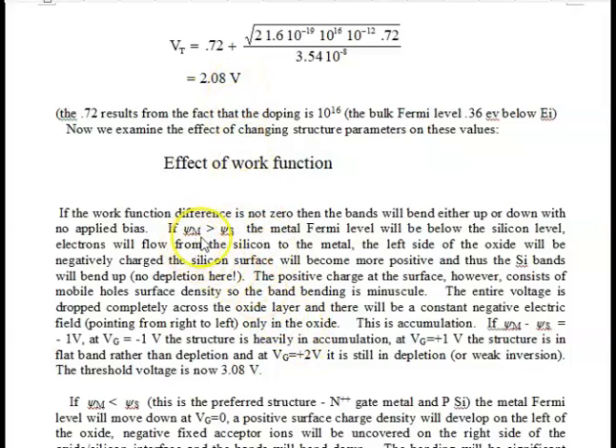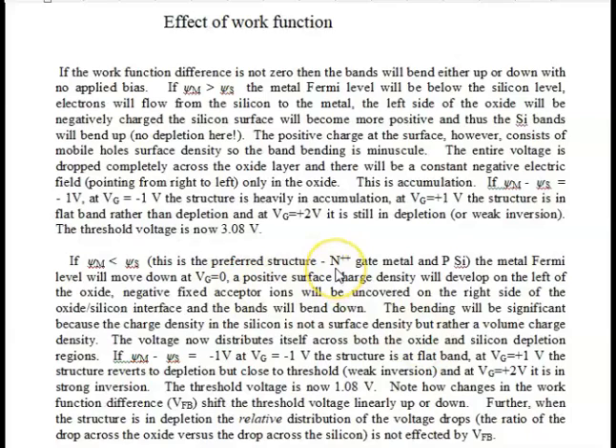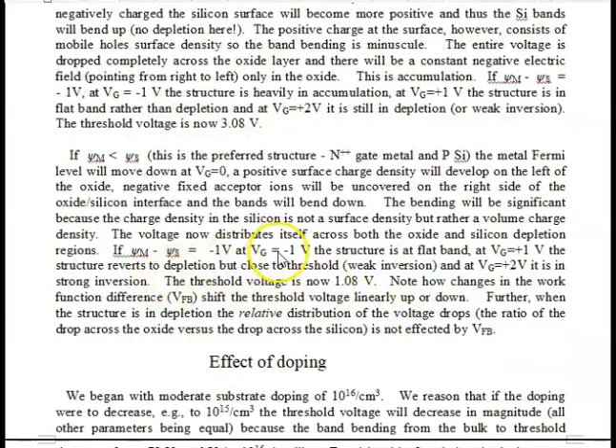Now, if we had a work function difference here of 1 volt, that gives us that difference of 1 volt here. And again, that is consistent with the fact that the flat band voltage is simply a shift, a translation, either left or right. And finally, if we look at the more normal situation, where we have metal work function less than silicon work function, think, for example, of an N++ degenerately doped gate metal for phi sub m, Fermi level higher on P silicon, and then we have a flat band voltage of about -1 volt. For Vg equals 0, we will have depletion. For Vg equals 2 volts, we're probably going to have strong inversion because the threshold voltage is quite reasonably low.